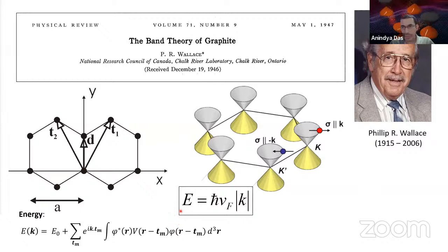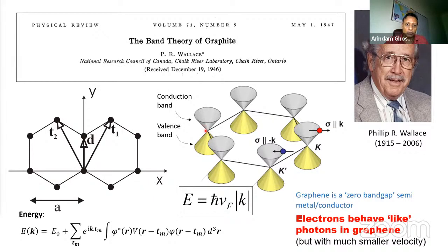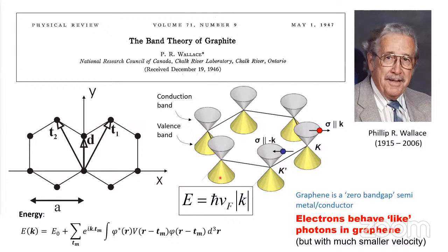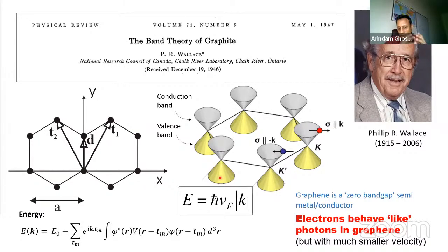So what Philip Wallace calculated way back in 1947 is that there is a cone, what is called a Dirac cone, along which the energy of graphene depends on its momentum. K is like a momentum, and E is the energy of graphene. And secondly, it's like a semi-metal in which the electrons are completely filled in the yellow part of the cone and completely empty in the upper part of the cone, which is called a conduction band. So it's like a zero band gap material where the conduction band and the valence band come together and meet at one particular point. And this point is called the Dirac point.